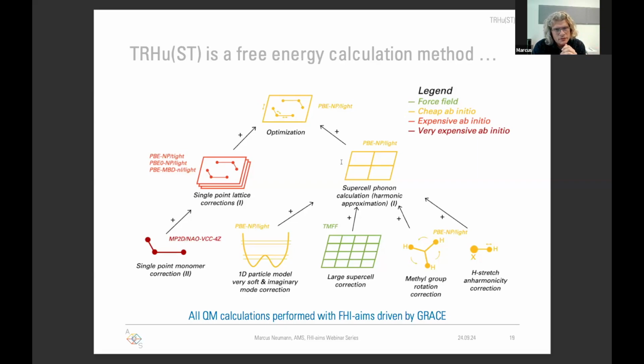But very often, and especially for certain molecules, there's a problem with electron delocalization error. And so we also do single point monomer corrections for the molecules in the crystal structure. And this is what, referring to the literature, I would call Beran's method. So I think Beran and his group were the first ones to show that this is really useful on a compound called ROY.